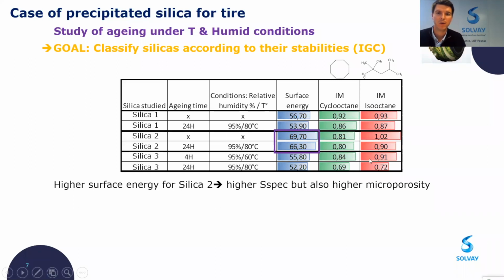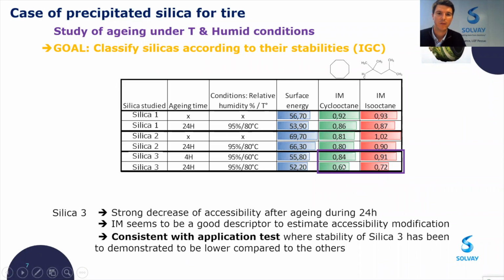And concerning the morphology index, as you can see here, this is very interesting because we are able to see the accessibility is modified during the aging, and especially for the silica 3. As you can see here, we have a strong decrease of the morphology index, meaning that we have lower accessibility compared to the other type of silica.